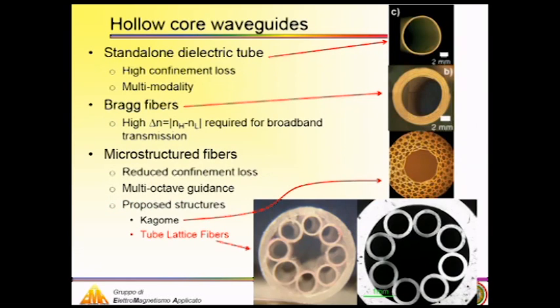Different structures have been proposed in the literature, starting from the simplest one, the standalone dielectric tube. It is very simple, but it suffers in general from high propagation loss and multimodality. There are also Bragg fibers, which have lower propagation loss, but in general not a wide transmission bandwidth. And then finally, those we are going to consider today, microstructure fibers. They allow a reduction of the confinement loss with respect to the other fibers, and they also have multi-octave guidance. Different structures have been proposed in the literature, as you can see from here. These are known as Kagome fibers, the top one, and these are two pictures of tube lattice fibers.